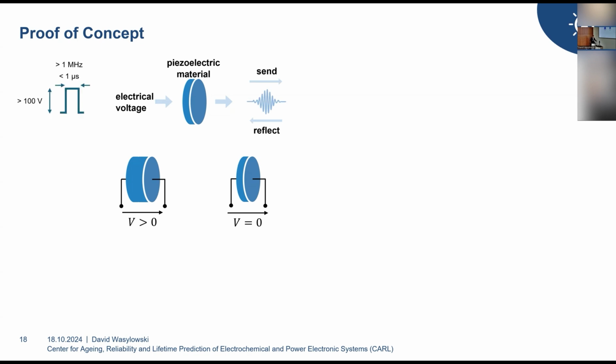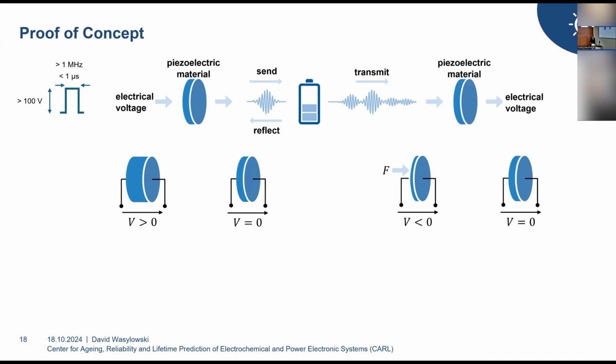And in practice, we use high voltage, so over 100 volt, and very short pulses, less than 1 microsecond, to apply on these piezoelectric materials to produce a sound wave. We then force the sound wave onto a battery. It passes through it, interacting with all of its components, and then is transmitted on the other side. And when we now place a second piezoelectric material in front of this transmitted ultrasound wave, it acts as a force on this piezoelectric material, compressing it, and therefore, using the same effect, also generating a voltage. So this is how we can produce and measure ultrasound. We call the right effect the direct piezoelectric effect, and the left one inverse, because just the right one was discovered first.